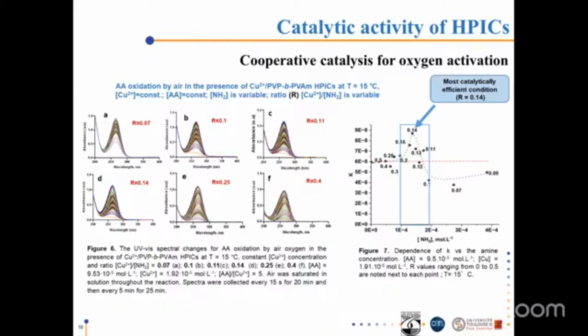And it turned out that in the absence of polymer, the reaction proceeds like in the presence of copper sulfate. When polymer is added in insufficient amount to fully complex all available copper ions, at a ratio more than 0.25, a slight decrease in the rate constant is observed compared to free copper sulfate.